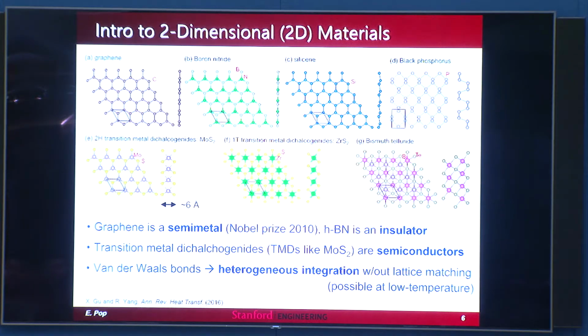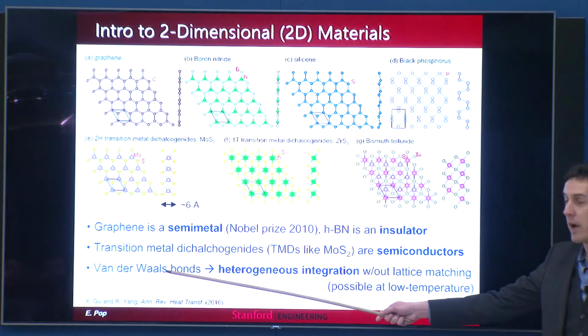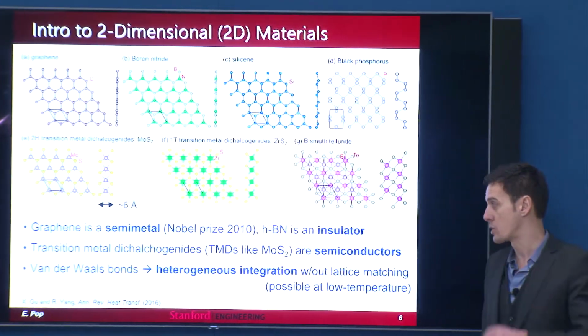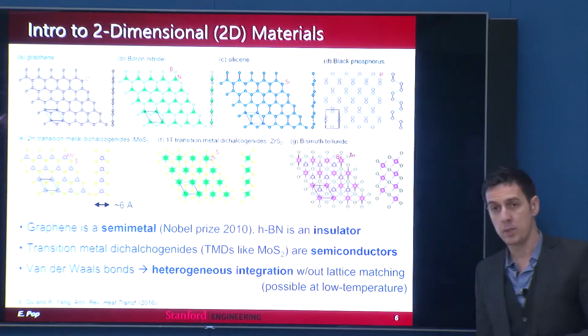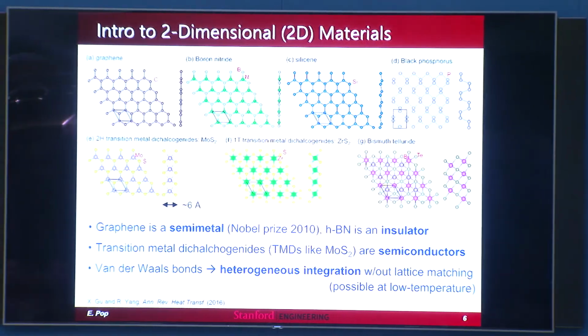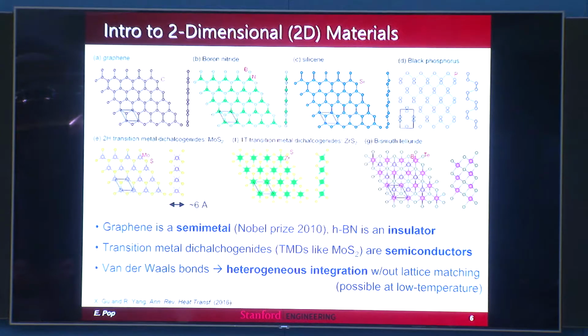What we like about these things is the fact that in plane they're bound by covalent bonds, but out of plane they're actually stuck with really, really weak van der Waals bonds. And that's what really enables this heterogeneous integration aspect, which I mentioned earlier, right? You can do heterogeneous integration without lattice matching. Whereas, of course, I'm sure if you're familiar with III-Vs, for example, a lot of work on III-V materials is doing heterogeneous integration by very careful lattice matching. Otherwise, you end up with a lot of defects and so on.